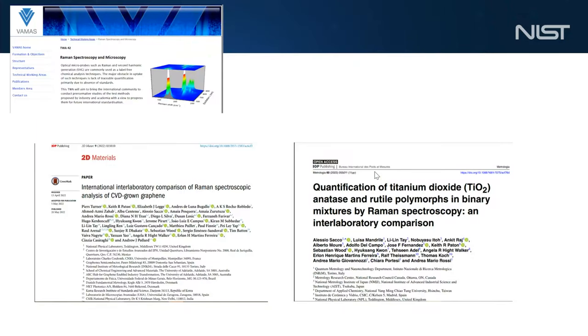We have validated that if you follow the protocol as written, you're going to get a result that is both precise and accurate. And all your other colleagues can do that too. I put up two examples here. One was on graphene and one was on titanium. These two materials are nanomaterials, well known in the community. One study we tested, again, these were two different protocols, of course, on two different materials. One of the protocols we found was inadequate and quite sizably so.